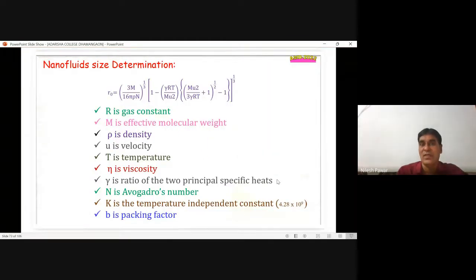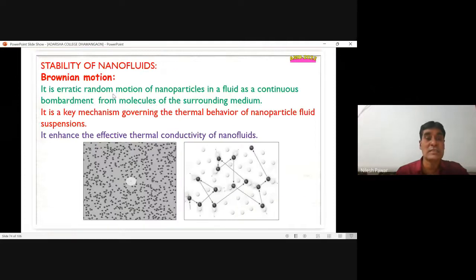And again, we determine the size of that nanofluid by using the thermoacoustical study. By using the pulse echo method, we find some basic parameters, and from that we compute a number of thermoacoustic parameters, and by inserting all these parameters in the standard formulae, we compute the r0, that is the intermolecular radius, and that is nothing but the size of that nanofluid. Okay, that is available in the medium. And definitely the size of this differs from the size of the nanoparticle, and hence we conclude that it is better for the study.